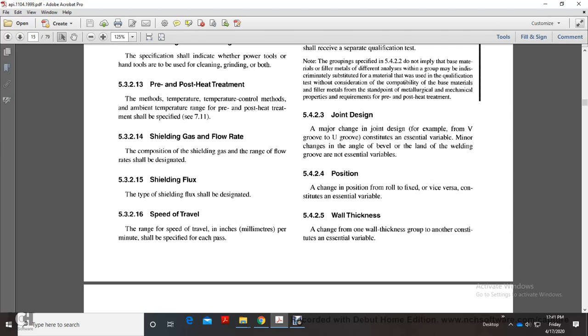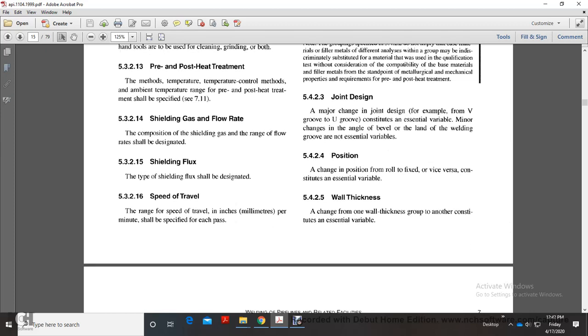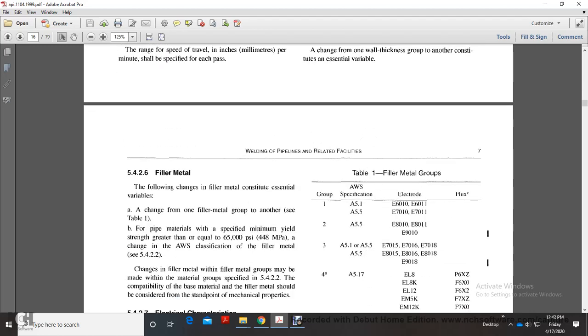5.4.2.3 Joint design. A major change in joint design, for example from a V groove to a U groove, constitutes an essential variable. Minor changes in the angle of bevel or land of the welding groove are not essential variables. 5.4.2.4 Position. A change of position, rolled or fixed, or vice versa, constitutes an essential variable. 5.4.2.5 Wall thickness. A change from one wall thickness group to another constitutes an essential variable.